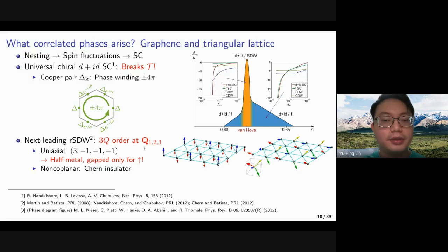And it will be the 3Q order ground state. That is, the ground state will have simultaneous formation of orders at Q1, Q2, and Q3. So in terms of different spin structures, we could have different ground states. The first kind is the uniaxial order, where the spins at Q1, Q2, Q3 point along the same direction. In this way, if we look at the lattice and at a unit cell, we'll see that there is a 3, -1, -1, -1 structure. And if we look at the band structure, it will realize a half metal, where it is gapped only for the spin up band and gapless for the spin down band.